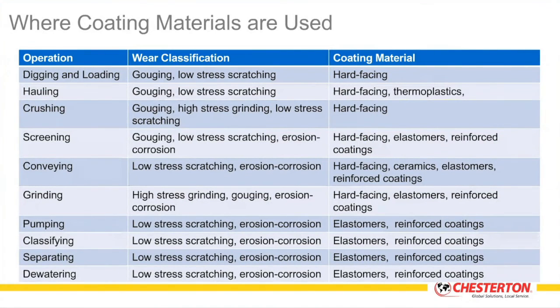Now, when we're looking at where coating materials will be used, depending on the operation or the process area, you'll define the type of wear that is occurring, and then you can choose the various materials. So this table here gives you the ability to look and say, okay, if I'm in the screening area, the typical wear that I'm dealing with is gouging wear. There is little high-stress grinding wear, but there is low-stress scratching abrasion, and there is erosion corrosion.